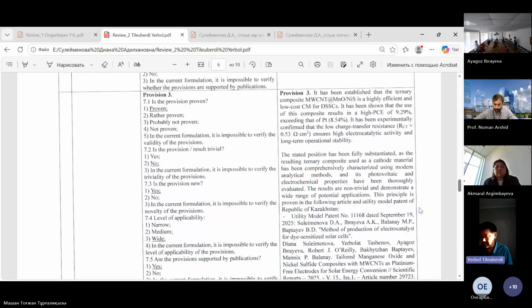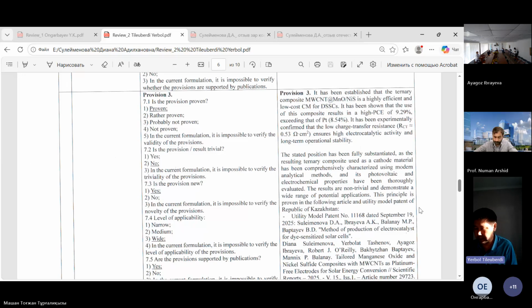So for provision 2, my comments: it has been published that the three-step solvothermal synthesis of iron cobalt sulfide nanowires makes it possible to obtain a counter electrode with reduced charge transfer resistance compared to platinum. It has been shown that DSSC based on iron cobalt sulfide nanowires achieves a higher PCE. These photovoltaic devices have been shown to have improved operational stability, whereas platinum-based cells show performance degradation.